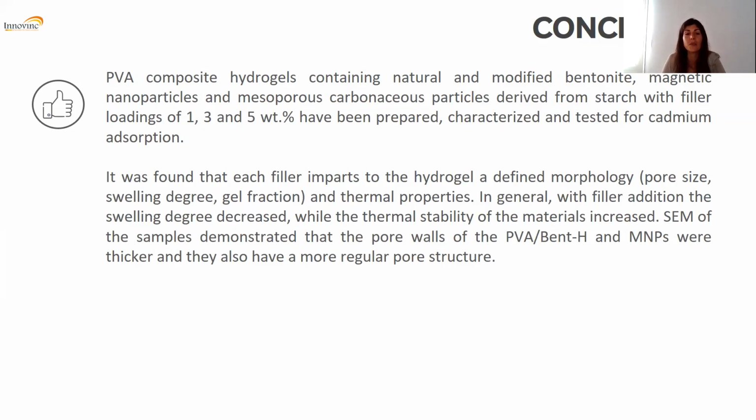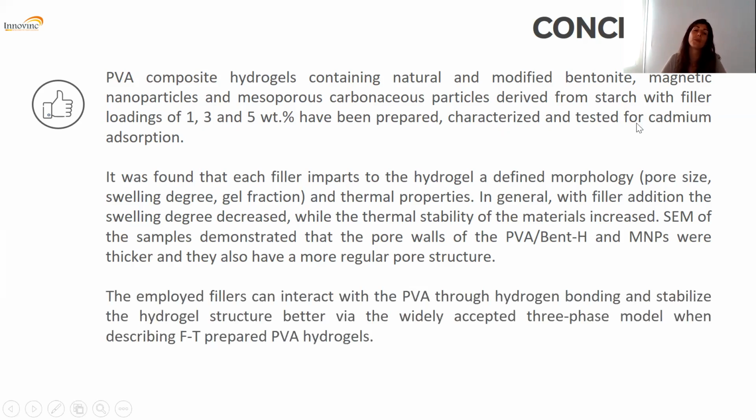SEM of the samples demonstrated that the pore walls of the PVA with acid-resistant bentonite and magnetic nanoparticles were thicker, and they also have a more regular pore structure. The employed fillers can interact with the PVA through hydrogen bonding and stabilize the hydrogel structure, in line with the widely accepted three-phase model when describing freezing-thawing prepared PVA hydrogels.